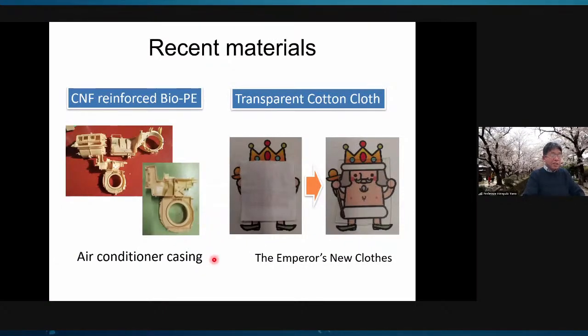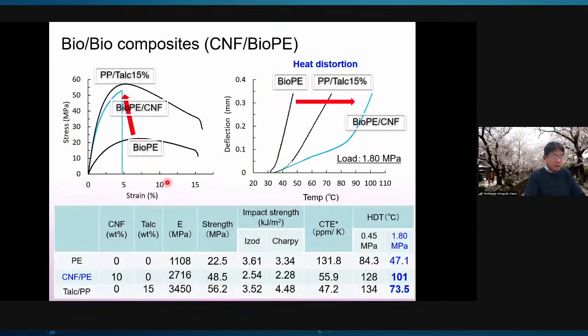And these are our recent materials. Left side is an air conditioning case using CNF reinforced biopolyethylene, and the right side is optically transparent cotton cloth. 10 weight % CNF reinforcement increases the rigidity of biopolyethylene from 1.1 gigapascal to 2.7 gigapascal. And interestingly, it attained a 30-degree higher heat distortion temperature, HDT, at 1.8 megapascal than PP talc composite. So the HDT of cellulose nanofiber reinforced polyethylene reaches around 100 degrees Celsius.